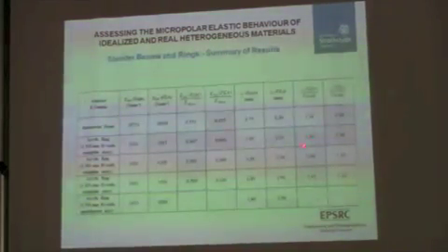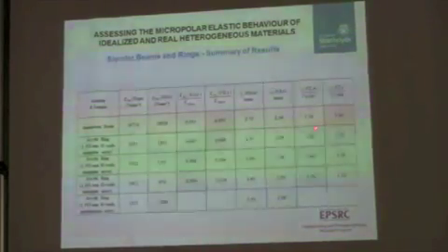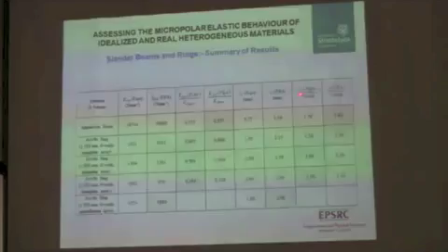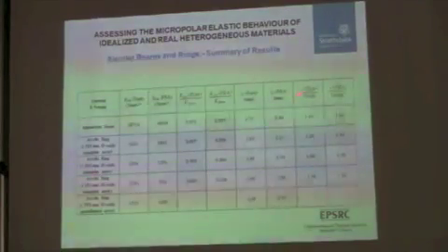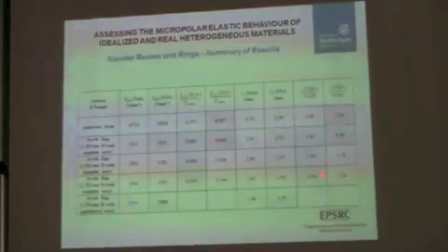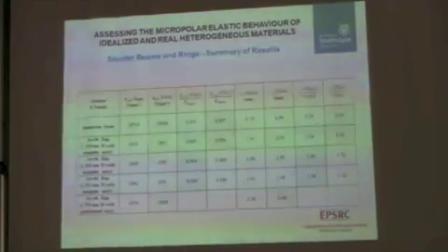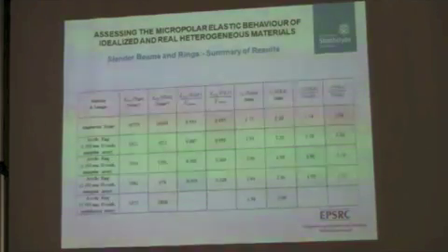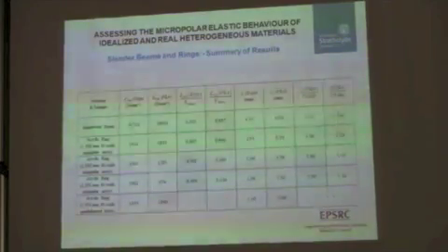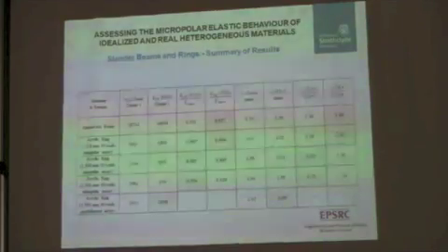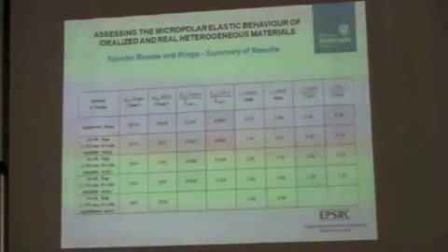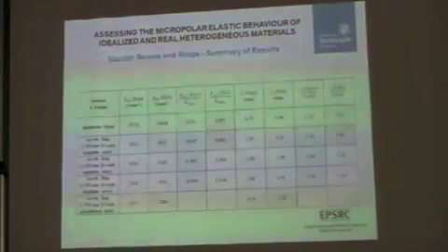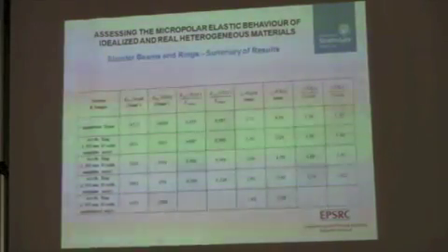If you look at the blue data here, this shows the dimensionless length scale, or the length scale normalised with respect to the void diameter, and there's a suggestion here that the length scale parameter scales with the void size, which is actually quite a nice finding, because there's a nice theoretical paper by Bigoni where he suggests this, and these results help to confirm that.